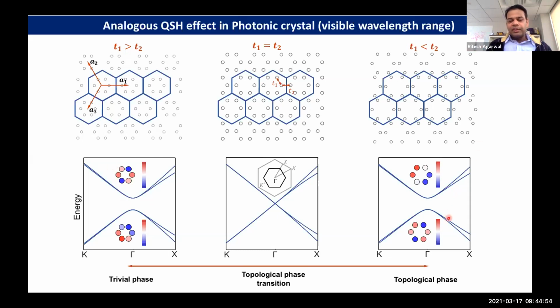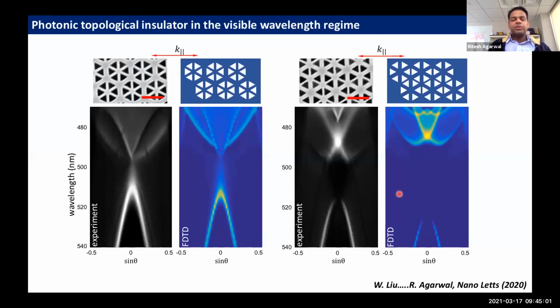And if we create an interface between these two structures, at the interface one can have these quantum spin Hall, topologically protected modes. So we fabricated these structures using silicon nitride and did k-space momentum spectroscopy. So this is in the trivial regime. This is the p band. This is a dipolar structure. It couples to the far field. That's why it looks bright. Here you can't see it, but there's a dark mode corresponding to the d orbital picture.